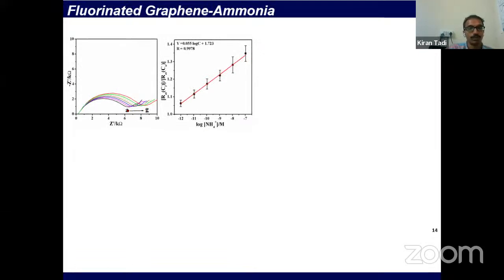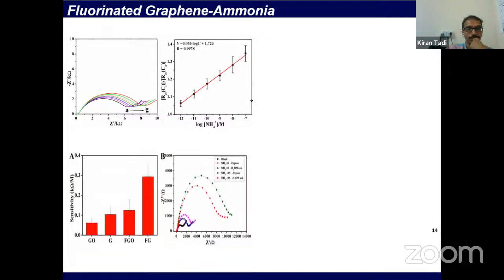When we slowly add ammonium ions, ammonium solution, into my electrolyte, the impedance of my electrolyte gradually changes. Interestingly, we found it works in the picomolar range and also the micromolar range. The sensor is working wonderfully.